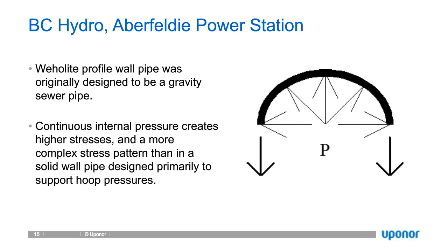Weholite pipe was originally designed to be a gravity sewer pipe. It wasn't anticipated that it would be used for continuous pressure applications. Gravity pipes usually experience pressures for only relatively short durations of time. And in normal gravity flow, the hydraulic grade line generally follows along at the top of the pipe, the obvert of the pipe. But with gravity flow, for sewers, there's typically periods where there is surcharge occurring and where you will get peak flows considerably higher than that for short duration.